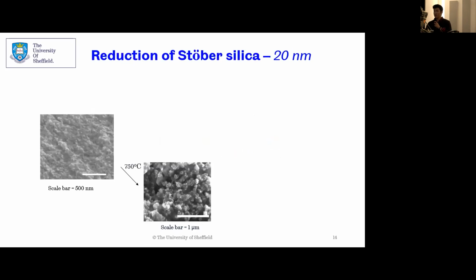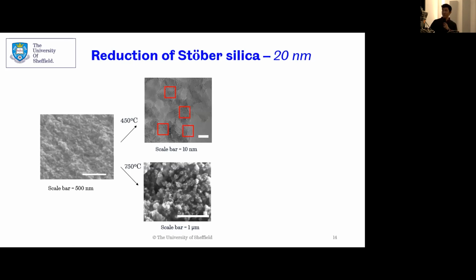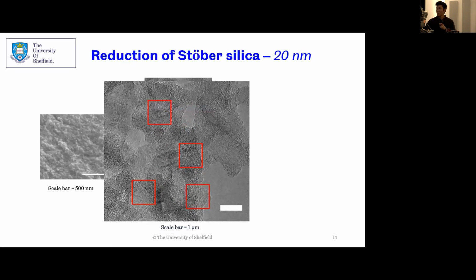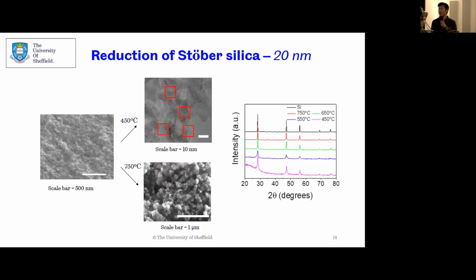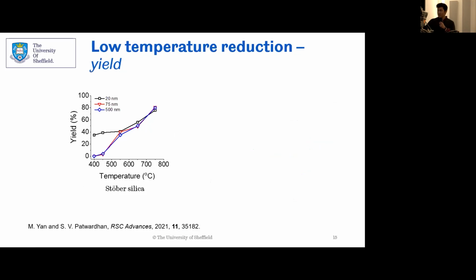This is the more interesting point. At 750 degrees Celsius, you can see sintering, so it's really hot. In the sample, throughout the sample, which means crystalline material is present. So there's crystalline silicon here, and to confirm this, the XRD shows peaks for samples reacted. This is in stark contrast to the other two that I've just shown, 500 and 75 nanometers. So there's a threshold here, somewhere between 20 and 75 nanometers, where particles will react at 450 degrees Celsius.